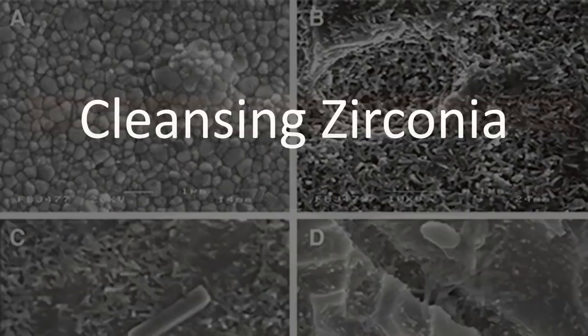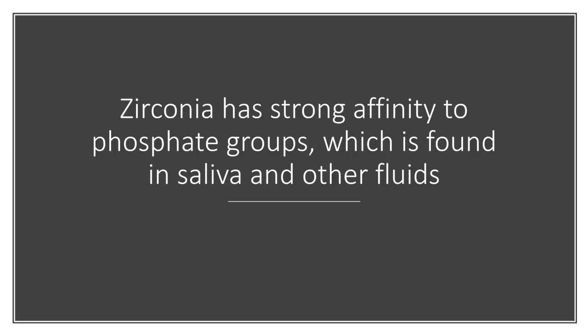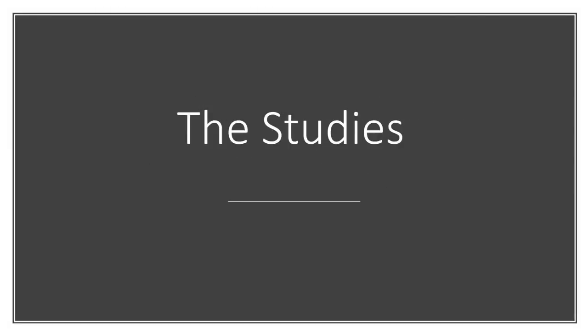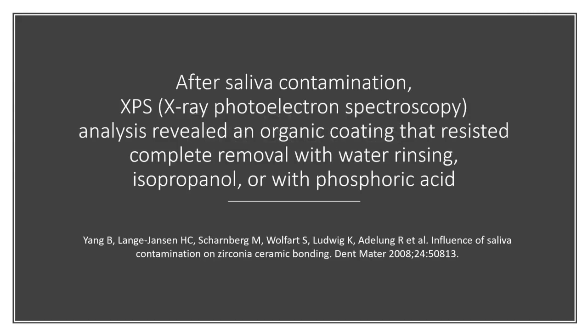Well, the first thing is how do you clean it? And it's amazing when I'm on the road teaching how this is really all done poorly. So if you're not cleaning the tooth right and you're not cleaning the zirconia right, then honestly, it's setting up for failure. So what does the literature say? Zirconia itself has a strong affinity to phosphate groups, which are found in saliva. So if it has a strong affinity, here's what happens. This is through the studies.